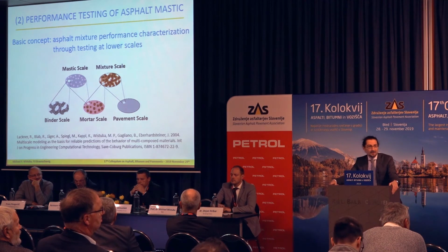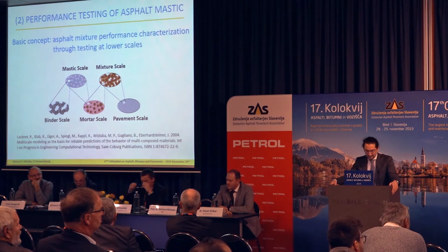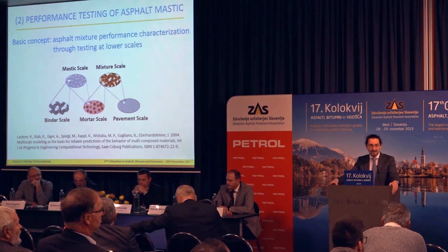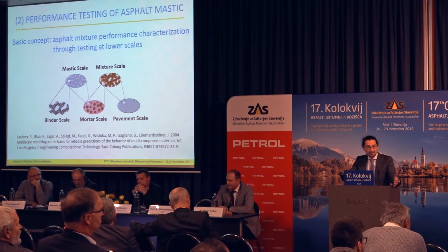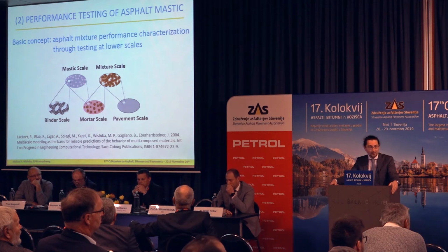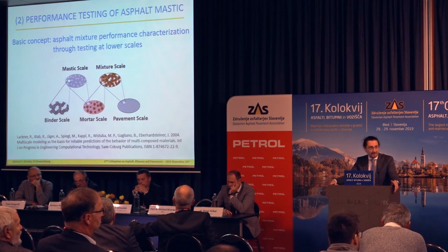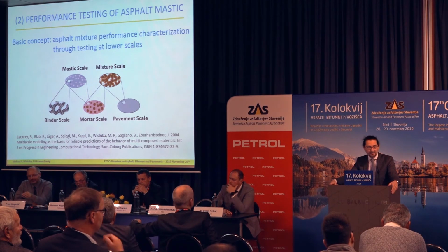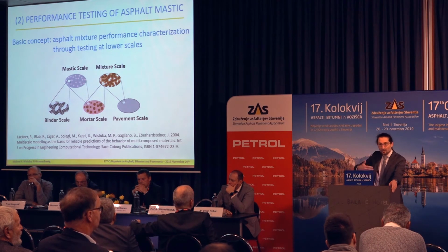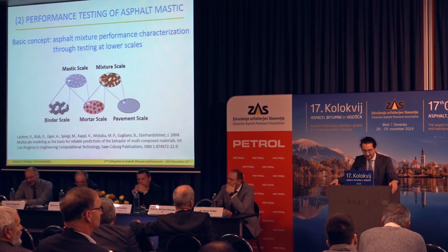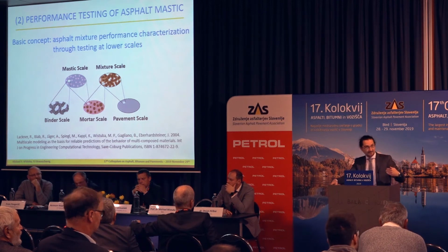So our idea is to focus on asphalt mastic testing, which follows the basic concept of a multi-scale model, which means that the properties of an asphalt pavement can be considered as a multi-scale problem, which means that performance of asphalt pavements is already mirrored at lower scales, which means that we could do binder scale testing or even better mastic scale testing to predict important key performance parameters of the asphalt mixture already at this lower scale.